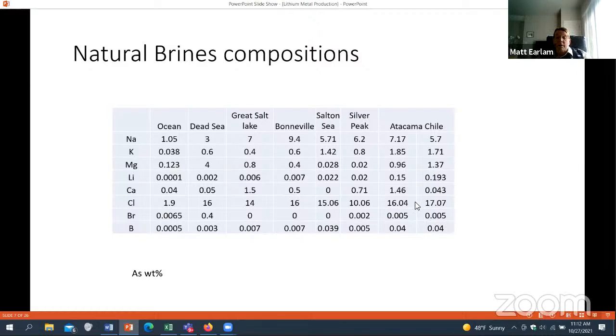Bromine, not so much. Chloride is obviously the counter ion for the cations in there. Magnesium, you'll see, is important, as well as sodium, because lithium has such a high decomposition potential. Any potassium or sodium that's excess to what we're trying to do will actually report to the cathode and contaminate our lithium, to the point at which you always have some potassium contamination in your lithium, and purification is required in some cases to remove the potassium from the lithium metal. I'll show you why that happens in a minute.